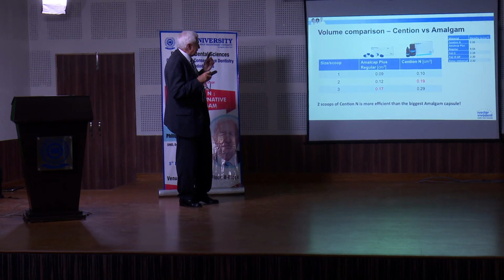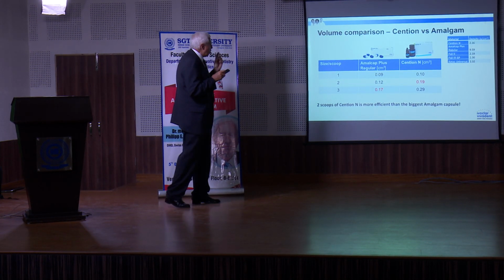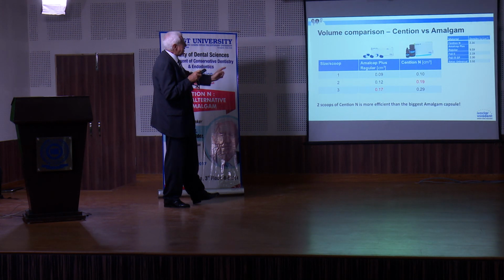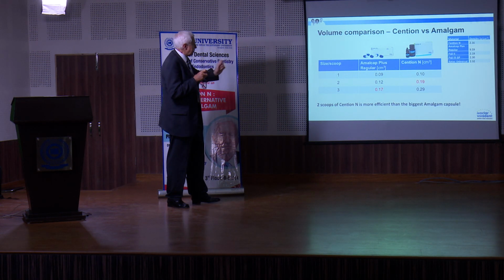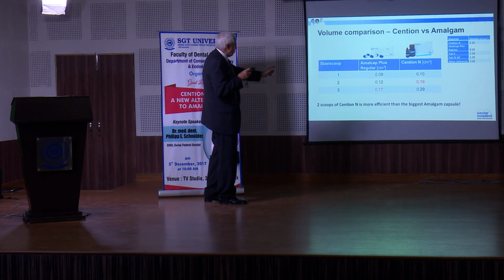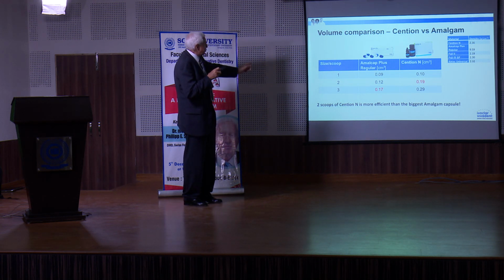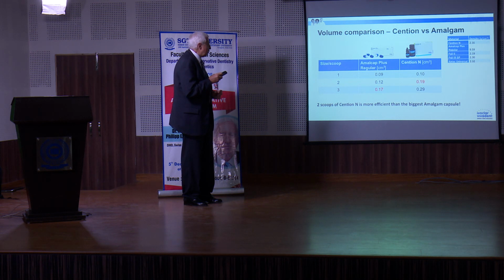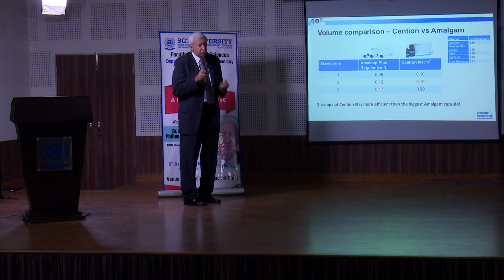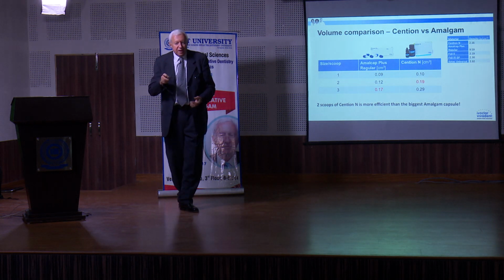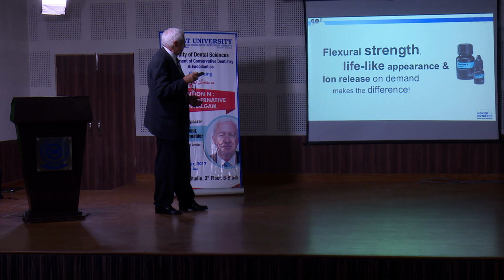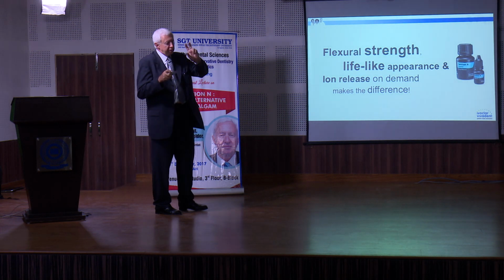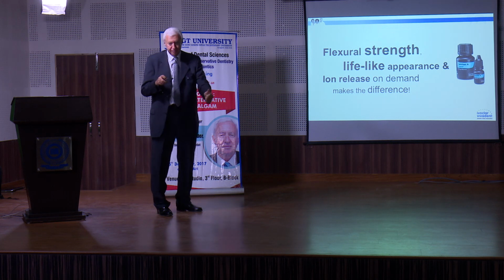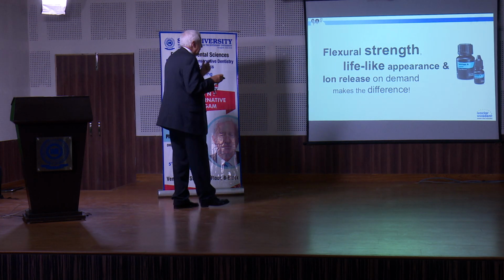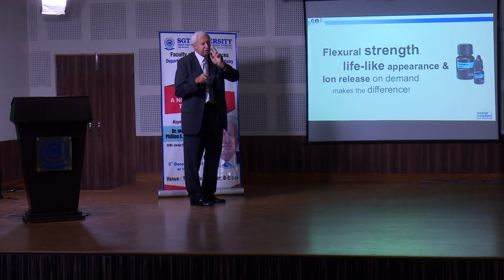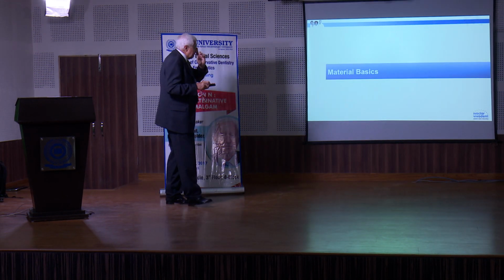With 2 scoops of Cention N, the second line is more efficient regarding the volume than a 3-spill amalgam. You see the 3-spill amalgam has only 0.17, and with 2 scoops of Cention N, I have 0.19. So these are considerations we really have to look at. So we have these 3 points. The flexural strength is enough, more than 100. Then it looks nice, and we have this ion release. This makes the difference.